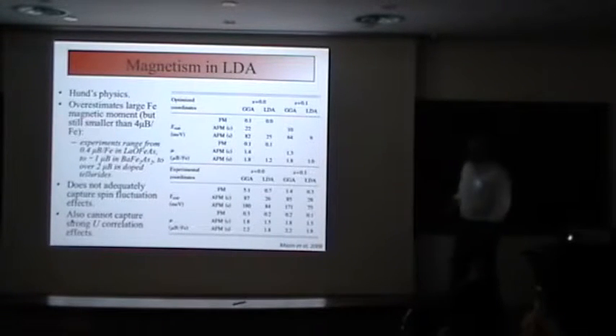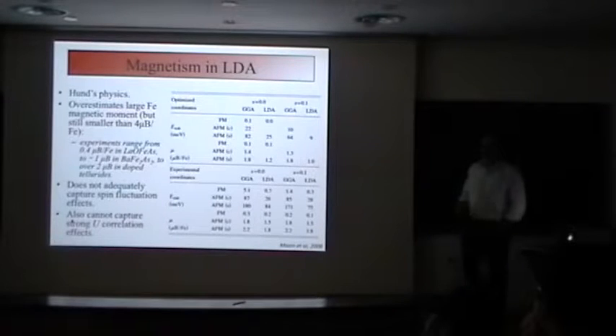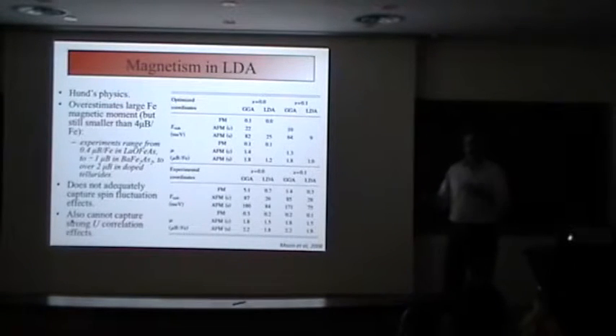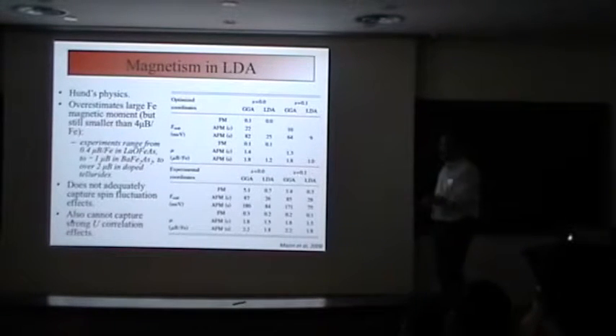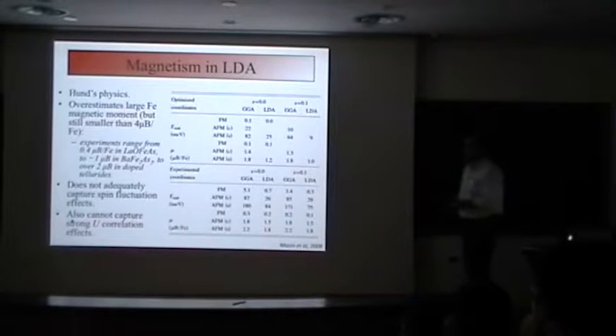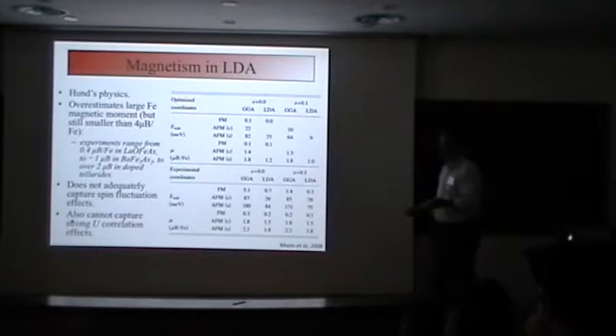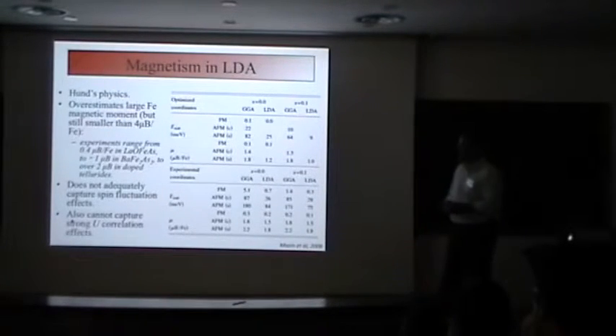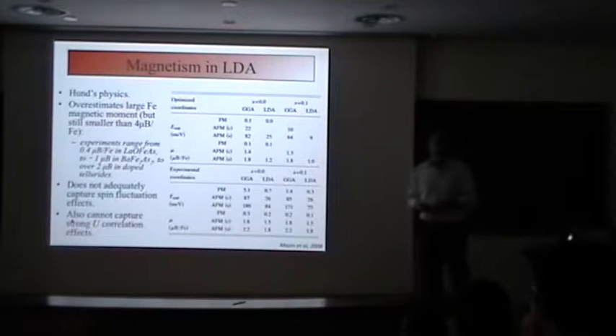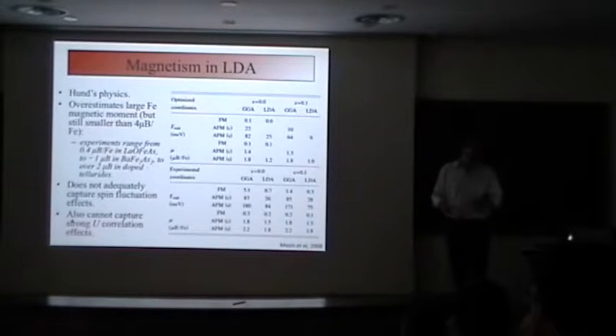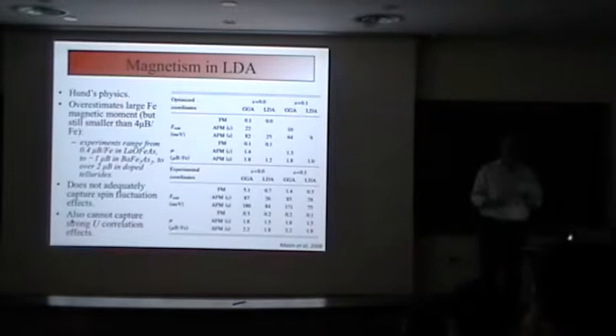The two issues about the weaknesses of LDA are: it's in essence a mean field theory, so it's not going to capture spin fluctuation effects which would tend to destabilize the overall magnitude of the moment. It also won't capture strong Coulomb Hubbard-type physics if that's involved - that's a well-known problem, LDA predicting metallic behavior in materials which are insulators.